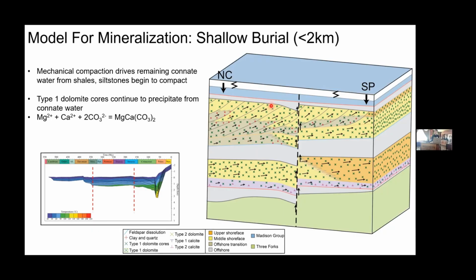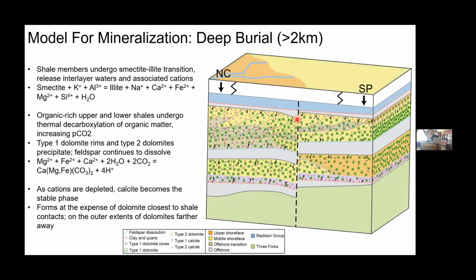From a fluid flow perspective, this would have been really sluggish compared to what we have observed in the meteoric influx event. But generally, the fluid flow would have wanted to go up and out towards the edge of the basin. But again, that would have been really sluggish and not necessarily a huge fluid flow. This is where the type 1 dolomite cores continue to form. And it wasn't until deep burial, so greater than 2 kilometers near max burial of the Sappington, that things started to get interesting, and we observed a lot of these diagenetic phases beginning to form.